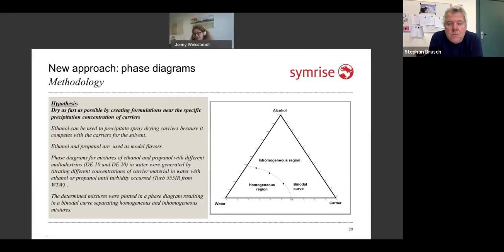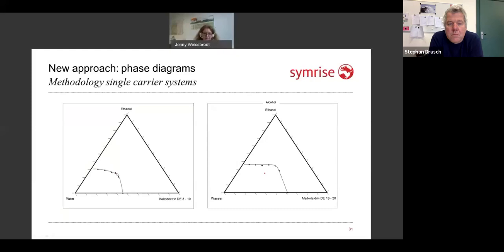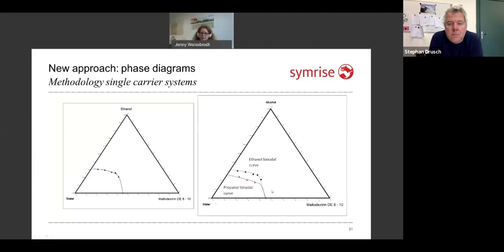Doing this, we could establish binodal curves for our system, which divide the whole diagram into a homogeneous and an inhomogeneous region. This curve is the thing which was very interesting for us. These are the curves we established for water, a maltodextrin with a low DE value, a maltodextrin with a high DE value, and ethanol. We even did the same with, for example, propanol and other completely water-soluble alcohols. It worked out. We found that there are nice binodal curves which we could establish with this method just by turbidity measurement.